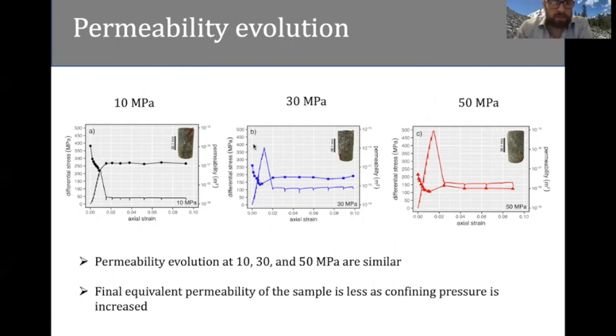So the experiment that we discussed before was the experiment performed at 10 megapascal, and we discussed how the permeability decreases as the sample is loaded up to the peak stress. And then after the formation of the macroscopic shear fracture, we see an increase in permeability. And then as the deformation is accommodated by sliding on the fracture surface, we see that more or less the permeability doesn't change up to a strain of about 10%.